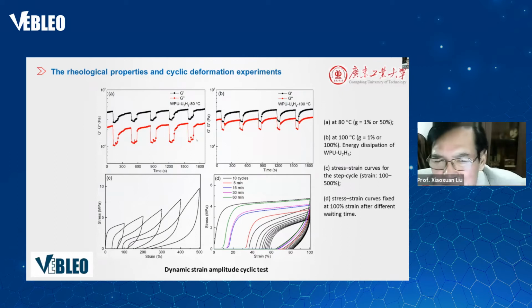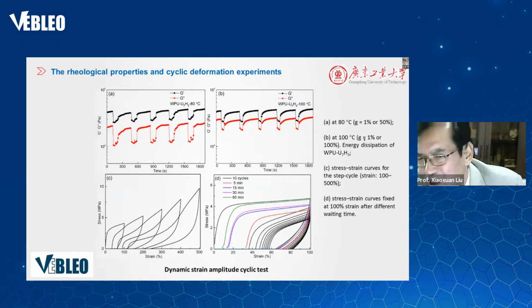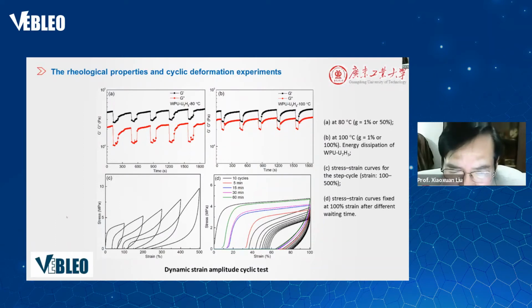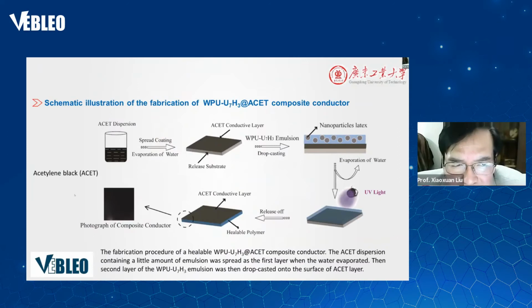At 80 degrees centigrade, the strain is 1% or 50%. B is at 100 degrees, the strain is 1% or 100%, and the energy dissipation. C is the stress-strain curves for the steps, with strain from 100 to 500%. D is the stress relaxation test fixed at 100% strain after different waiting times.